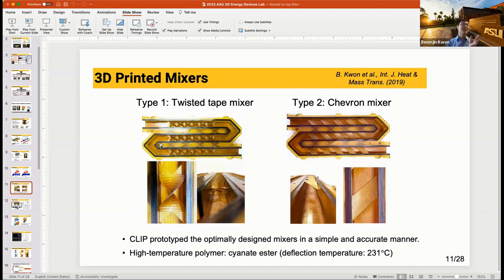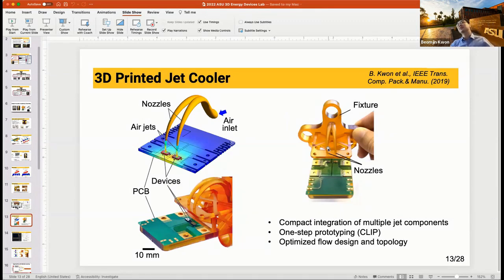As I said, the roughness we measured was around 100 or 200 microns. Our pixel size is 25 micrometers, but the feature we make does not exactly have 25 micrometers. We try to solidify 25 microns, but the UV light disperses slightly into the neighboring region, and it creates some roughness features. We measured that using microscopes in the lab and observed a few hundred, maybe about 100 micrometers. But considering the size of the channel and the nozzle size here, the roughness effect was not so huge.